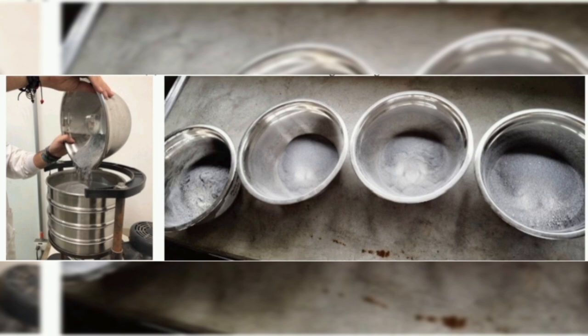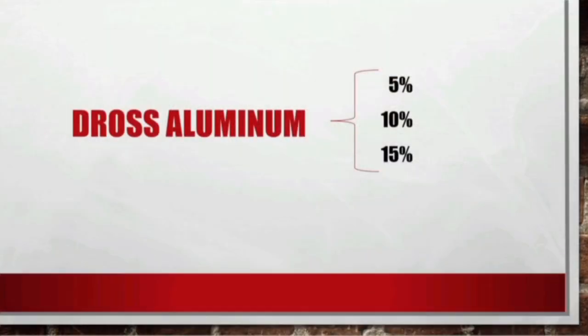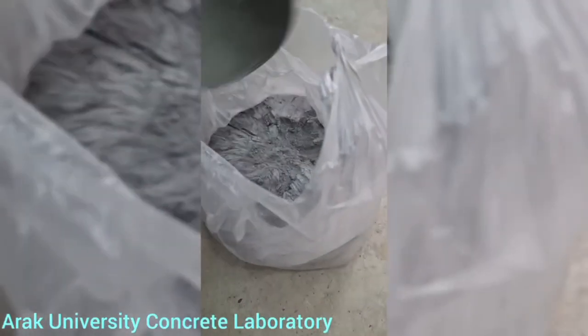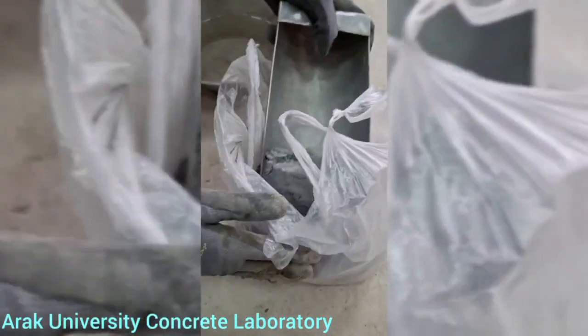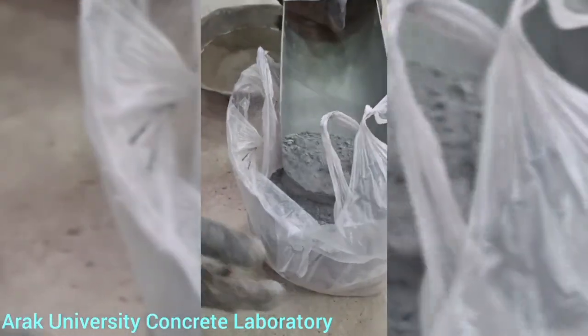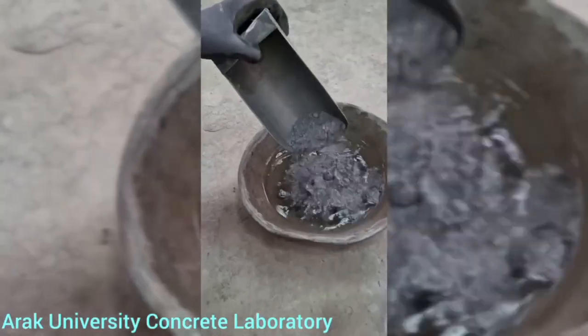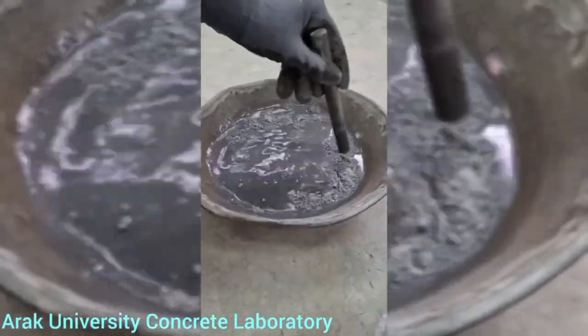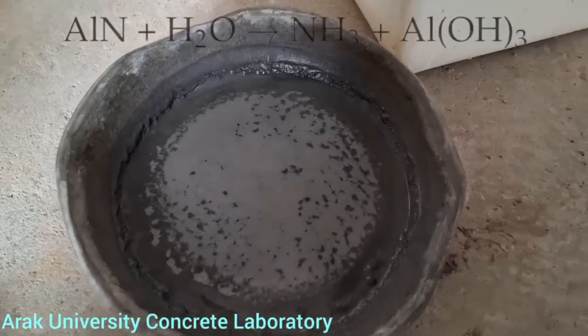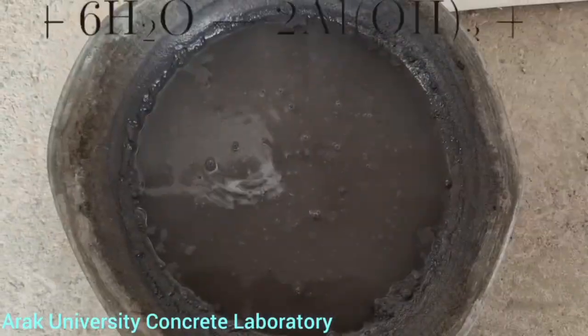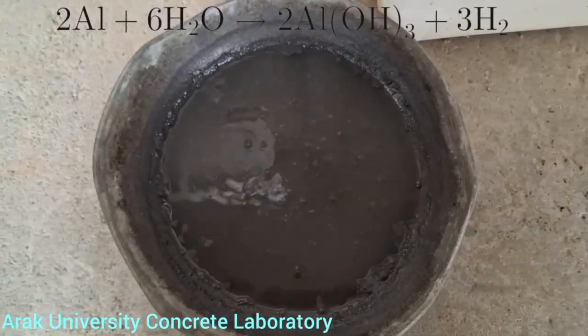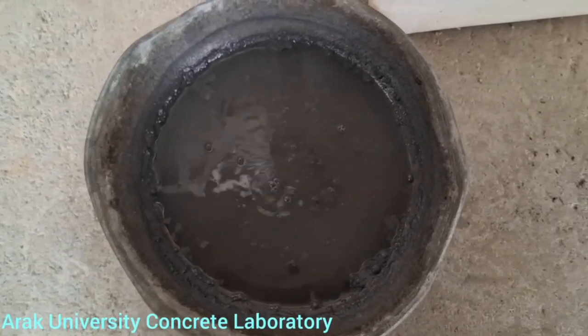In mix design, different replacement percentages of cement with aluminum dross are tested: 5 percent, 10 percent, and 15 percent, with the goal of finding the optimal ratio. To check reactivity, gray dross is mixed with water. In the initial reaction, vapor rises. Over time, the reaction releases hydrogen gas, producing visible bubbling. This shows that dross reacts with moisture, a factor that must be considered in concrete mix design.